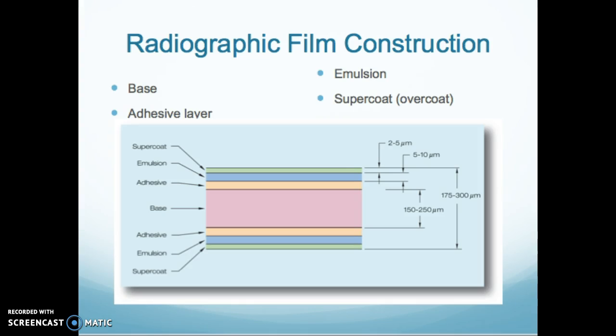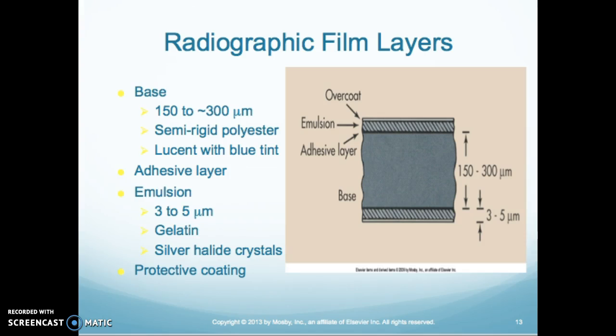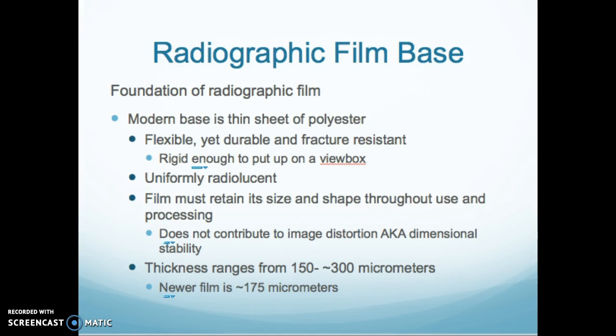Okay, so film construction. You have your base layer, then adhesive, emulsion, and then a super coat. We're going to cover each one of those. So the base is about 150 to 300 micrometers, and is semi-rigid polyester with a lucent blue tint in it. It has the adhesive layer on top of that, and the emulsion is anywhere between 3 to 5 micrometers. The emulsion is a gelatin with silver halide crystals suspended within it. On top of that, there's a protective coating.